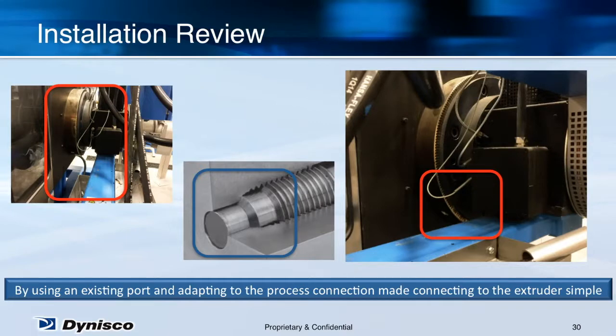The best location for measuring online rheology is before the die on an extruder. In the application shown, this customer has a tight window in between the screen changer and the underwater pelletizer. He did have an existing auxiliary temperature sensor located there with a half 20 connection. This is shown in the blue square in the middle. This port is quite common in the extrusion industry with pressure and temperature sensors as well as rupture burst plugs. By utilizing this port, it eliminates the need to modify the extruder and was already in the proper location to get the best reading for the finished polymer's rheology.